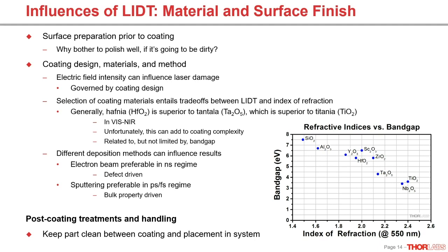Next, you're going to want to select coating materials that have a high damage threshold. For example, if you use niobium as your high index material, you may have a very nice coating, but you're not typically going to have great laser damage threshold performance. In general, you're going to want to use silica as the low index material. And then for the high index material, you're going to want to choose between one of these others on this chart. And laser damage threshold does tend to scale roughly with band gap.